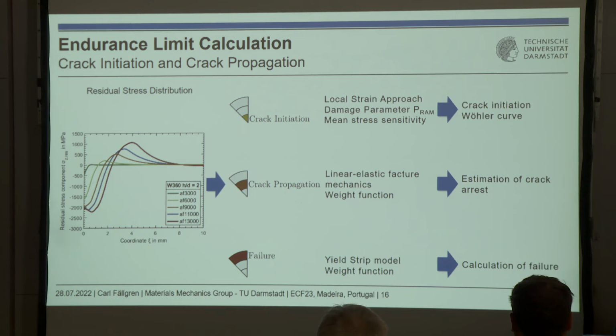Then you have crack propagation, so you can use linear elastic fracture mechanics with a weight function, especially designed to use for these kinds of specimens that we had. With that, you can estimate if crack arrest is going to occur or not. And also, we used the yield strip model with a weight function to calculate the failure, but I'm going to focus on this estimation of the crack arrest in this presentation.